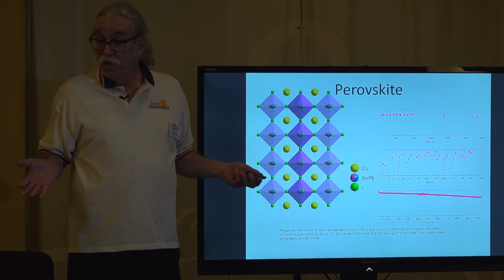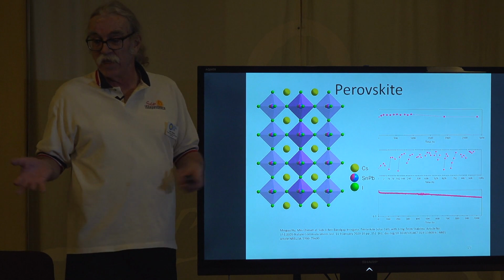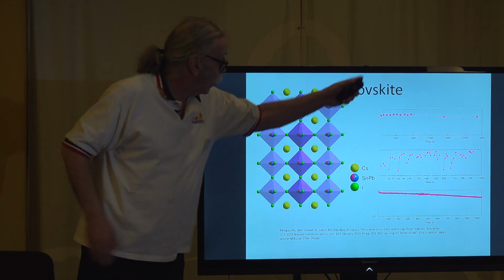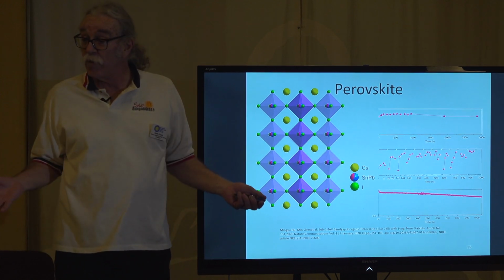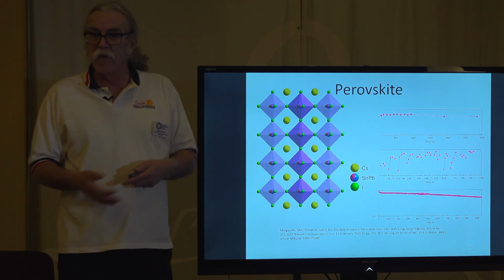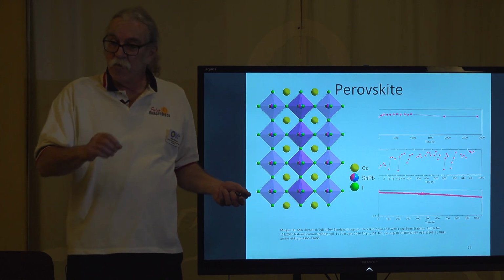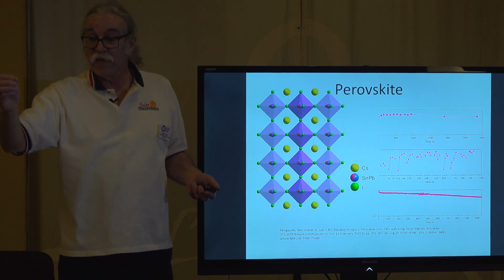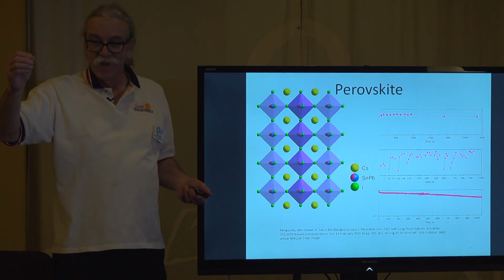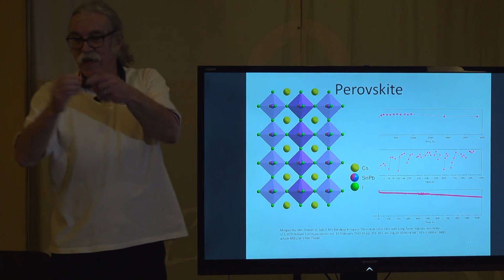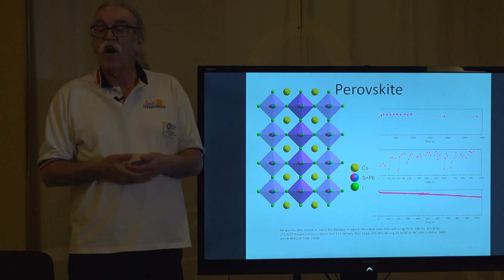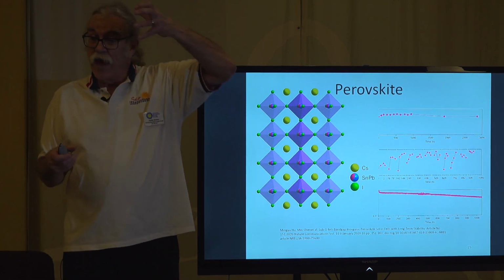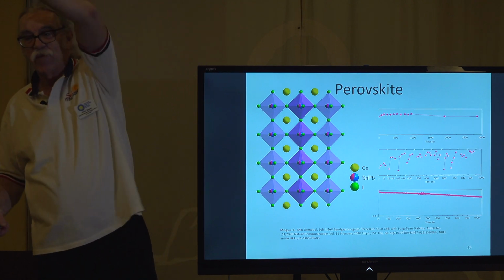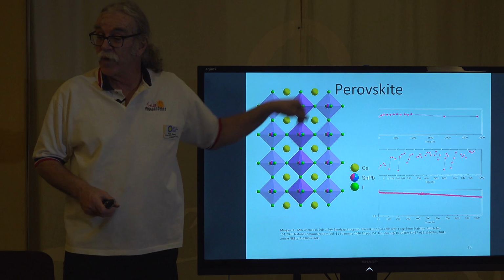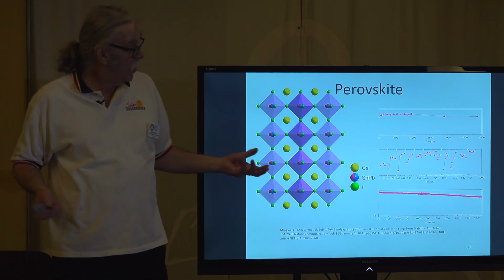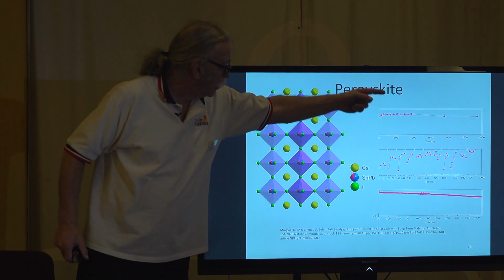I mean, the only thin films after 10 or 15 years of development were CIS and CdTe that came anywhere near those numbers. So the only problem was that they were unstable. Oh, and a small measurement problem. They have incredible hysteresis loops. What does this mean? This means that if you change the voltage, the light level, the temperature, or anything, it may take a couple minutes to stabilize again. Okay, well, if it's degrading spontaneously and it's that unstable, it's very hard to test. In fact, custom software had to be developed. We had to go and sit there at the maximum power point and watch it stabilize. And so the bottom line is these things are a little bit like batteries in terms of really slow response time. And they're unstable, but they're getting better.